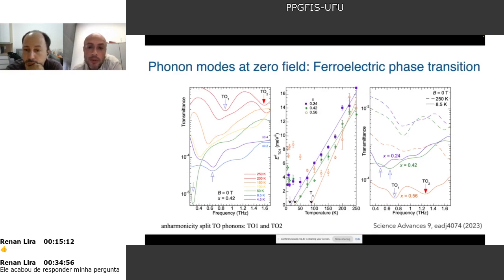Here I'm showing 3 samples, 0.2, 0.4, and more or less 0.6% of tin. Then the frequency of the phonon decreases, but then increases, right? Then you can see here that it increases. And this is because with the addition of tin, the critical temperature for the ferroelectric transition can occur at positive temperatures. For example, for let's say here 0.6 is more or less like 80 Kelvin.